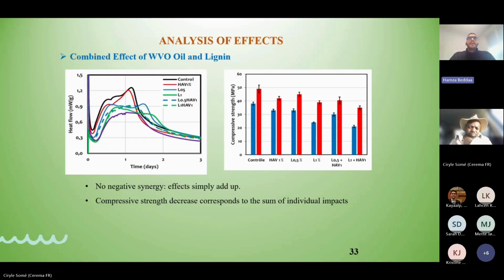So here we want to combine the two additives in the same cement paste. So we want to study the interaction between oil and lignin in order to see if there is something new to see. Maybe if we put them together, that could improve the quality of the cement paste, or maybe decrease the quality further. So here we can say that the effect on the hydration is just the sum of their individual impacts. So no negative synergy is observed. So no new effect is observed. Just a combination of these two individual impacts.